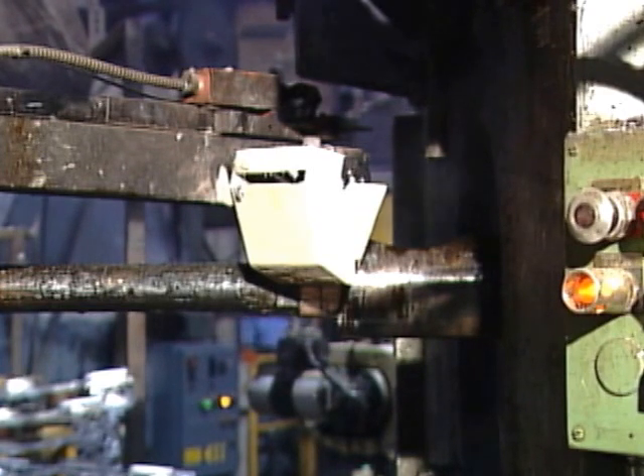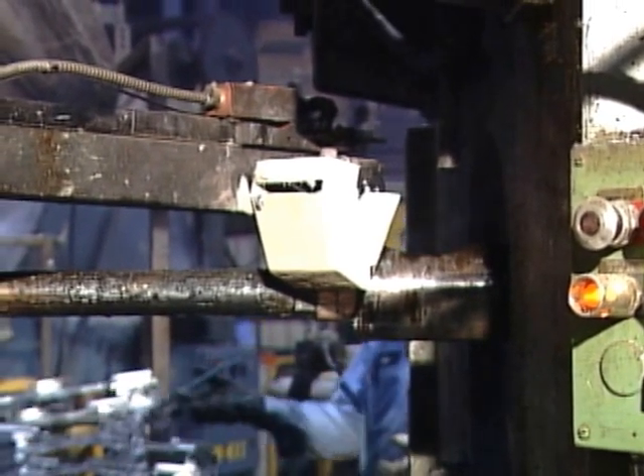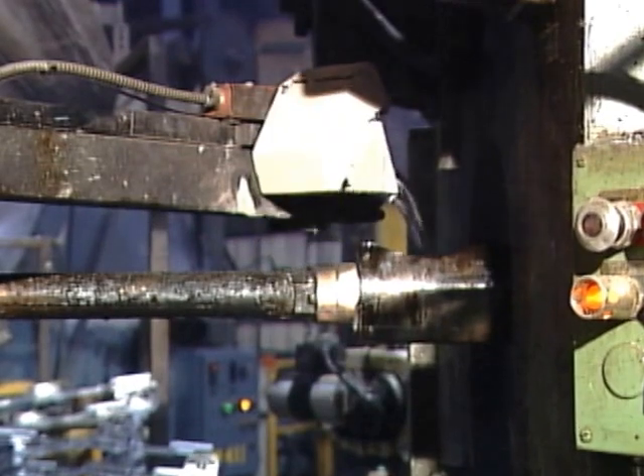It can be detrimental to part quality to have the ladle arrive at the machine any sooner. If the ladle is allowed to wait too long, the metal will begin to cool. As shown in this infrared footage, you can see how fast the dipper cools as the ladle waits for the diecast machine to close. It is unfavorable to cycle time if the diecast machine waits for the ladle.